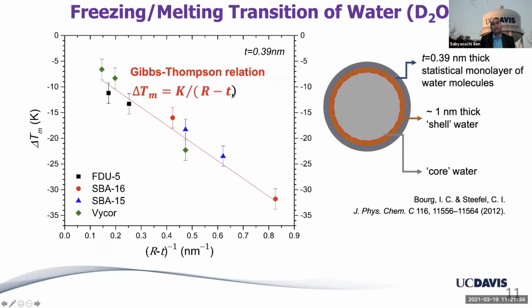which is sort of a monolayer of water that would be stuck and not doing anything, because it is strongly adsorbed on the surface of the pore, or this is the pore-liquid interface monolayer that does not do much. And we found that this t is about 0.39 nanometer, in excellent agreement with simulations by, say, Bourg and Steefel. For one, there are many others who did this kind of simulation of water in nanopores, and they saw that there is a statistical monolayer of water molecules with about this thickness, that's shown in blue, that does not do any activity and never freezes.